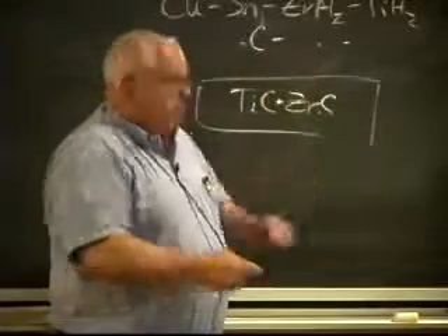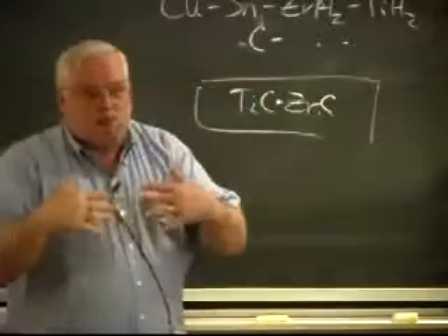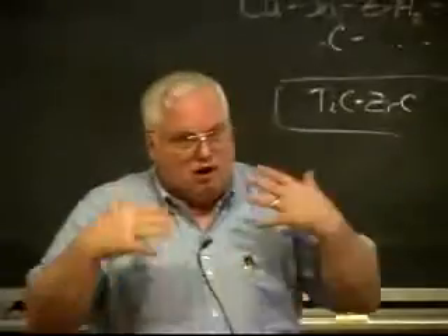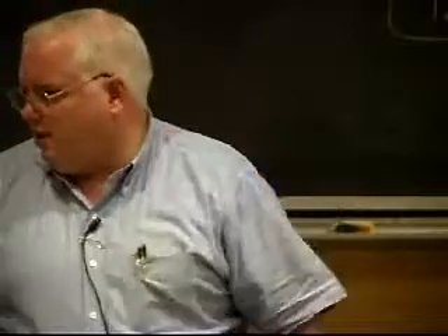These ceramics have low coefficients of thermal expansion, and the copper has a high coefficient of thermal expansion. The guy was right about that. But the whole composite braze alloy had an intermediate coefficient of expansion. And we had a finite element model, but the reviewer rejected it because he says no copper alloys have that, even though we provided him the data. He just didn't want to believe it. And at this point in my career, I'm not going to deal with these morons. So we published it somewhere else.